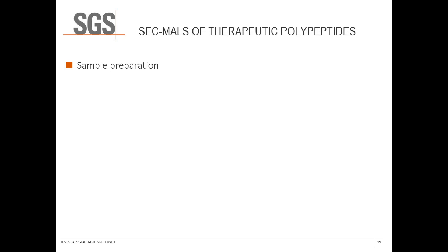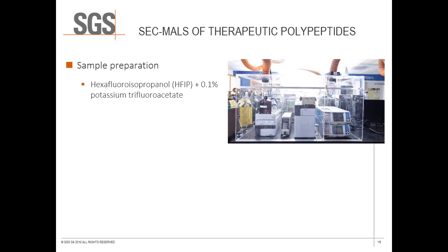In order to achieve total dissolution, prevent column interactions, and limit polypeptide intramolecular interactions, a specialty mobile phase of hexafluoroisopropanol, HFIP, containing 0.1% potassium trifluoroacetate was used for dissolution in SEC. HFIP is a highly polar corrosive solvent used most frequently for analysis of polar organic compounds such as polyamides or polyesters. Polymer Solutions has an SEC system dedicated to analysis in HFIP, which is enclosed in a specially constructed fume chamber for safety. In addition to the safety challenges of HFIP, this solvent is very dense.